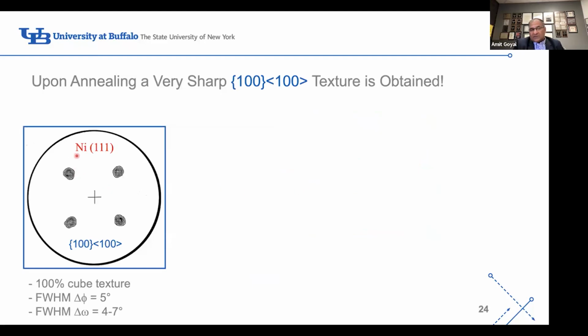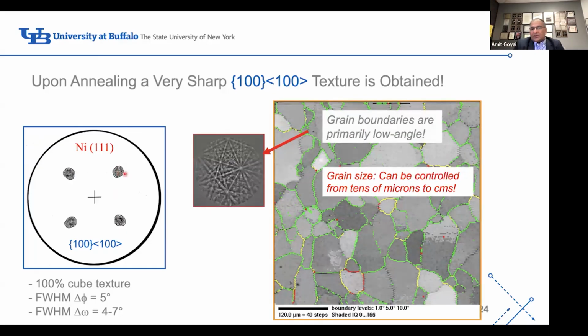So if you had a single crystal of nickel and you took a 111 pole figure, this is a single peak here, shows the A-axis orientations, and because there's fourfold symmetry in the cubic metal, you get 4 peaks. Here, these same peaks are slightly broadened. But there are still grain boundaries here, except they're all low angle boundaries. You're looking at now, every pixel here is an electron diffraction pattern. This particular image is created purely from orientation. Like I said, every pixel is an electron diffraction pattern. The image is created by about 100,000 diffraction patterns, and the green boundaries are all less than 5 degrees. So now you can imagine if I had a tape which is a kilometer long, which looked like this, and the superconductor also had orientations less than 5 degrees, I could potentially get very good current transmission.